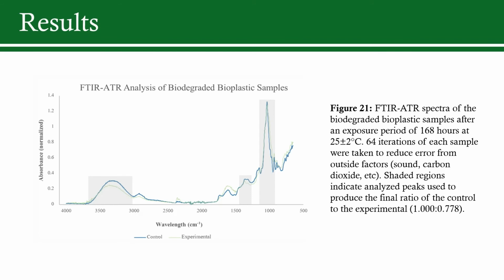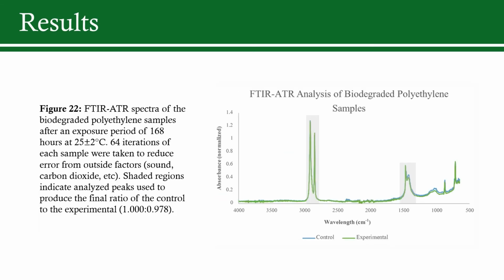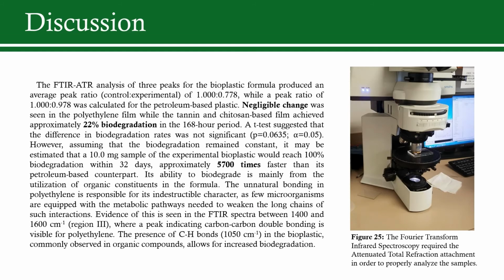Analysis of the soil degradation FTIR spectra showed 22% degradation after 168 hours for the bioplastic, while only a 2.2% degradation for the polyethylene film. The t-test suggested that the difference was not significant with the p-value equaling 0.0635. However, assuming the biodegradation was constant, the biodegradation rate of the bio-based film is approximately 5,700 times faster than its polyethylene counterpart.